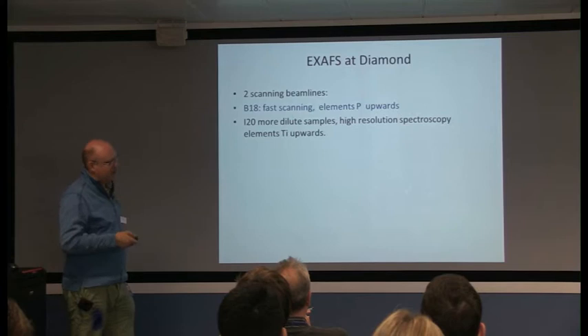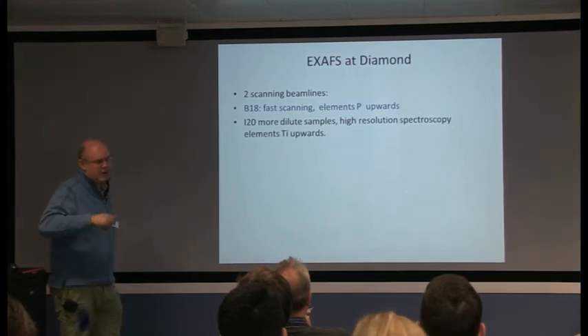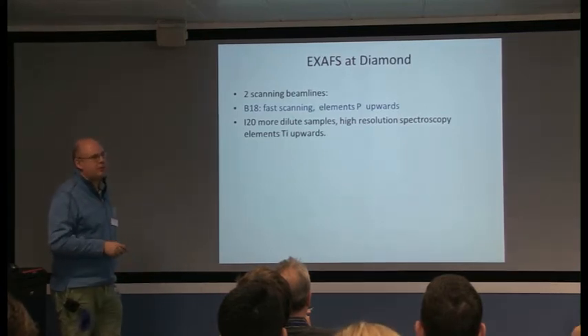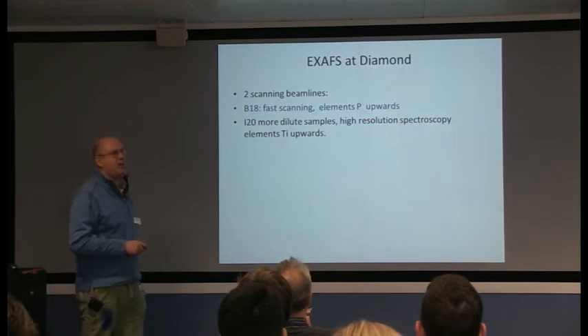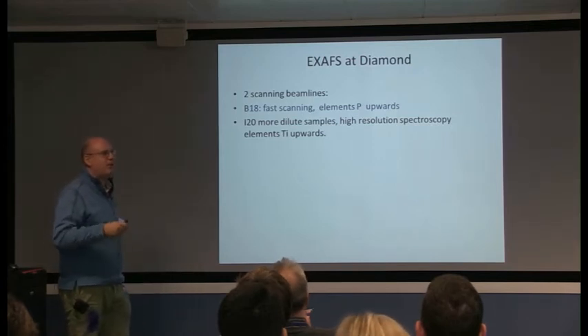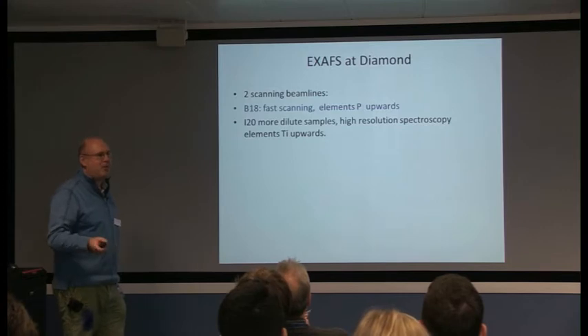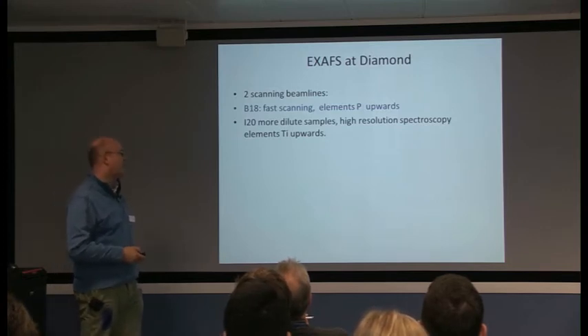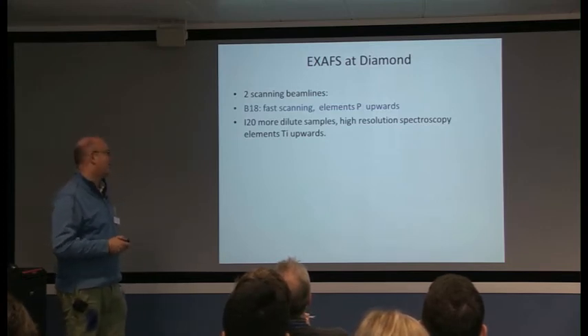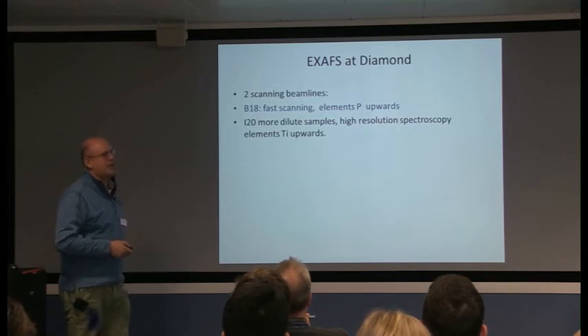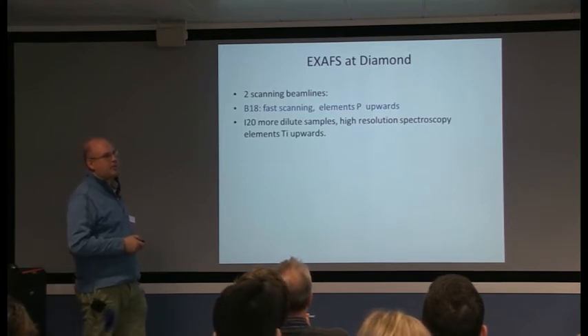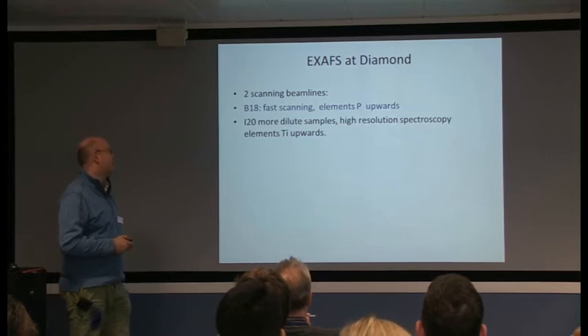B18 does fast scanning, can do elements from phosphorus upwards, and down in a mineral environment to somewhere in the low hundreds of ppm. In a biological environment it can go a lot lower, but mineral environments are more absorbing of X-rays, so you tend not to be able to get quite as low—probably down into the high tens of ppm for an organic type environment.